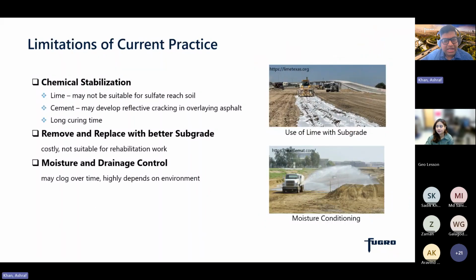With that, let's look at the current practices, like how the agencies are taking care of the problem. One of the mostly used solutions is the lime or the cement. But the problem is, lime has an issue with forming ettringite in the presence of sulfate. So it is not suitable where the soil is sulfate rich. And also, cement will make the soil more brittle, which may lead to the reflective cracking in the overlaying asphalt layer.